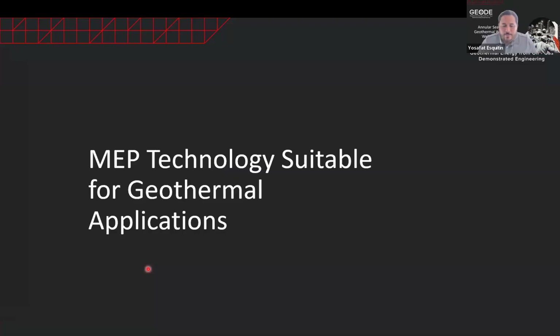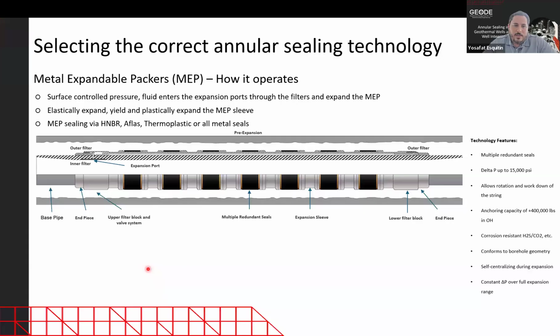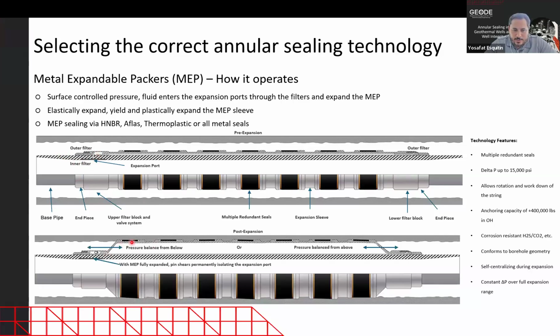So I'll talk a little bit about the metal expandable packer technology that is suitable for geothermal applications and is one of the unique technologies that has been qualified and tested to geothermal conditions. This metal expandable packer is an external casing packer mounted on a casing string. Through surface pressure, you put pressure into the casing, and pressure is diverted into the packer. As pressure goes into the packer, it plastically yields the metal, conforming it to the different sections in the well. Whether it's open hole or cased hole, it will conform to the entire surface of the well and create that annular seal. Once it's fully set, the communication from the bore to the annuli is closed, and then the communication from the upper or lower annulus is enabled to go into the packer chamber.